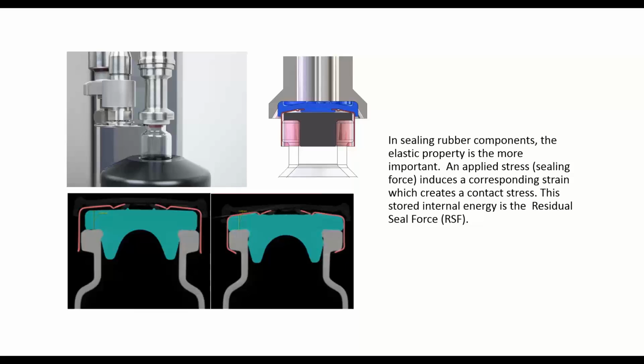The outside diameter of the rubber has actually increased. It's now equal to or even greater than the diameter of the flange of the glass. It's been compressed in shape and in the height of the flange of the rubber. And what that does is that the applied forces create a strain in the rubber which forms a contact stress. And that contact stress is what makes the seal and holds the seal and allows us to maintain that seal throughout the process. And again, when we talk about that, that's an amount of stored energy in the compressed rubber stopper, and that's our residual seal force.